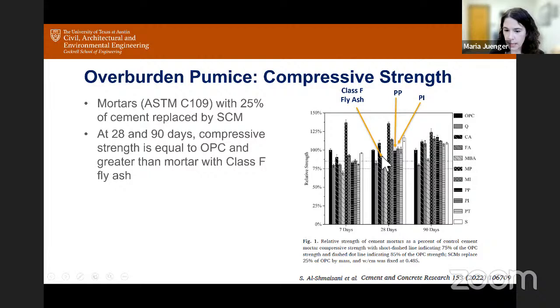If you look at the fly ash, it's above the 85% line, but not as high as the Portland cement by 28 days. If you look at the pure pumice and the impure pumice, they end up being actually quite similar to the Portland cement at 28 days and higher than Portland cement at 90 days. So they're actually outperforming a class F fly ash in compressive strength, which suggests that from a performance perspective, at least with respect to strength, they're good substitutes for fly ash, better than fly ash.